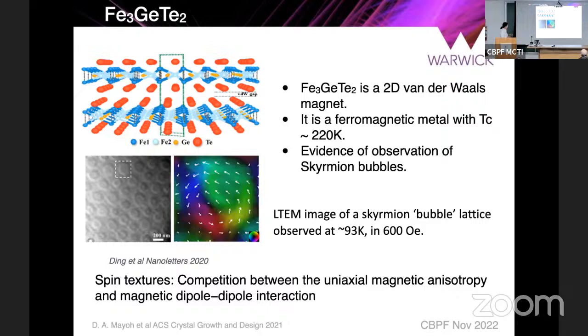So this was imaged in the FGT material at 93 Kelvin in a field of about 600 oersteds, but they also claimed that you can remove the field after you stabilize these skyrmions and warm up the material, and the skyrmion lattice is still stabilized, okay? So there's a lot of interest. But what you will find, contrary to what I've said so far, is that this is not a non-centrosymmetric structure.